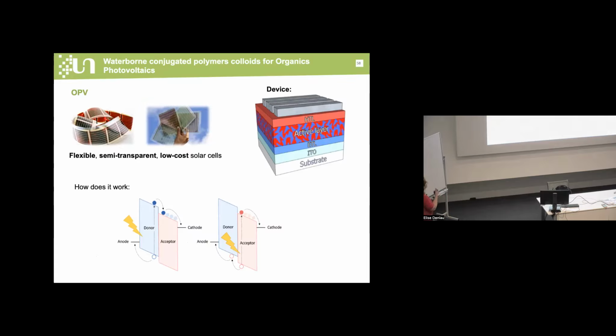Organic photovoltaics are very promising materials in solar cell development because they are flexible, semi-transparent, and low cost. The OPV devices are composed of an active layer, which is inserted between two electrodes. This active layer is composed of at least two semiconducting materials: one electron donor material, represented in blue, and one acceptor material, represented in red. Both materials are carefully selected, such that the band gap of the acceptor is deeper than the band gap of the donor, so the HOMO to LUMO distance,